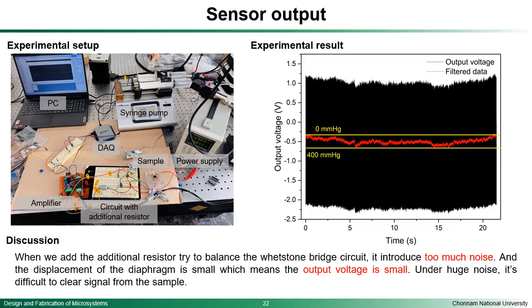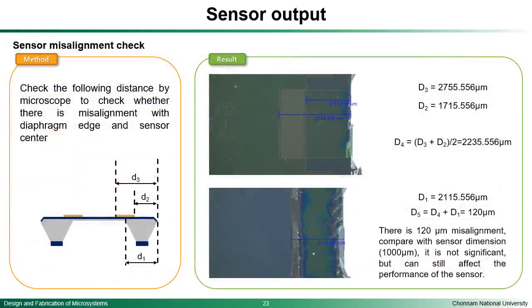The first main reason is the diaphragm issue. The thickness was too thick, so the displacement is not very large and the sensor output is not very good. The second one is the resistor part. The four resistor values are not balanced, so when we use the additional circuit resistors, it introduces a lot of noise. But if we do not use the additional resistors, the voltage change cannot be detected. Another possible cause of the sensor's low output is sensor misalignment.